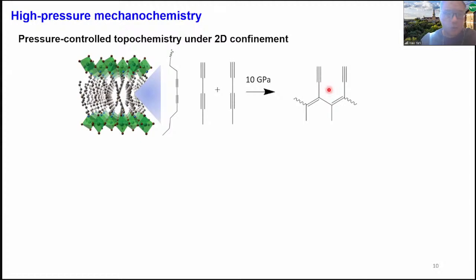Now, one of the twists that we did here that's different from the literature is that we're doing this reaction in a two-dimensional confinement. We have collaborators that synthesize a two-dimensional perovskite with the conjugated diacetylene as the organic spacers in between the lead bromide layers.